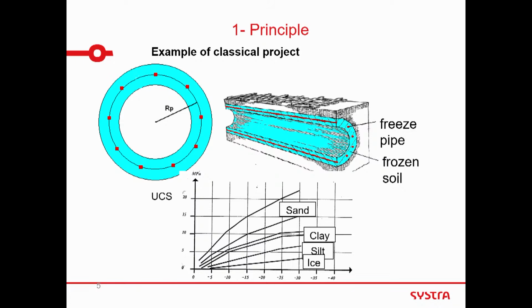But as soon as you get reliable data, you find the water content. Because of the design, you want to have an annulus of, let's say, 1 meter, because the stresses in this annulus when you excavate work with 1 meter. In this case, you compute the volume of water, and you get the energy at 80% of what is required. So then we can do a lot more refined calculation, but in terms of energy, this is the way for a good pre-design.